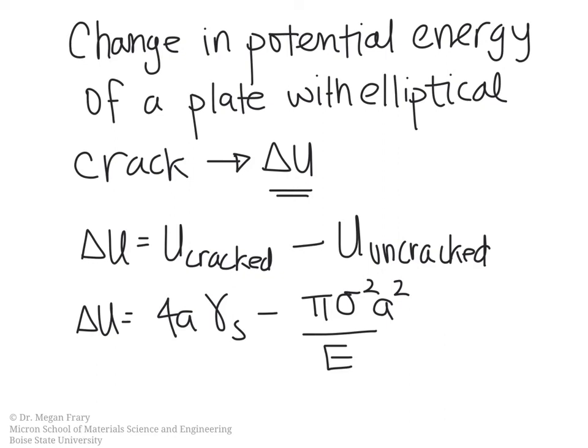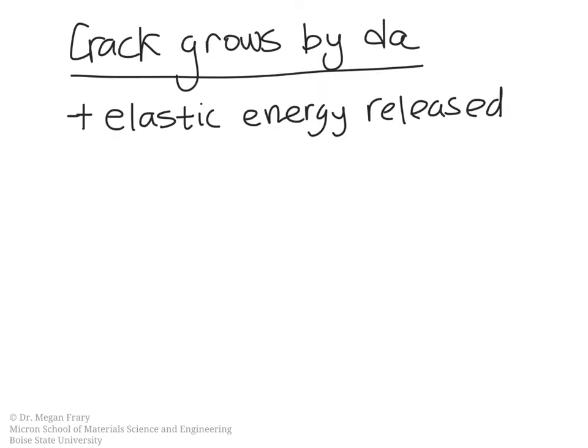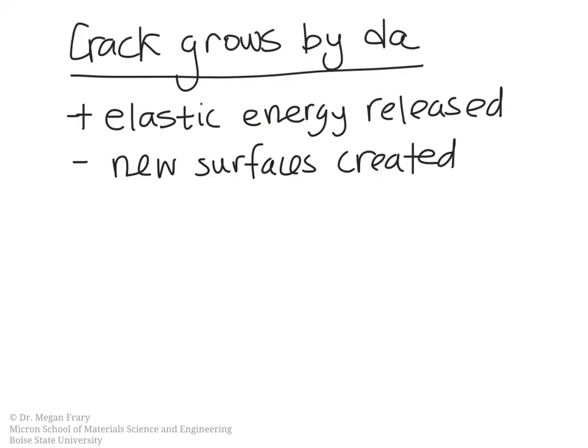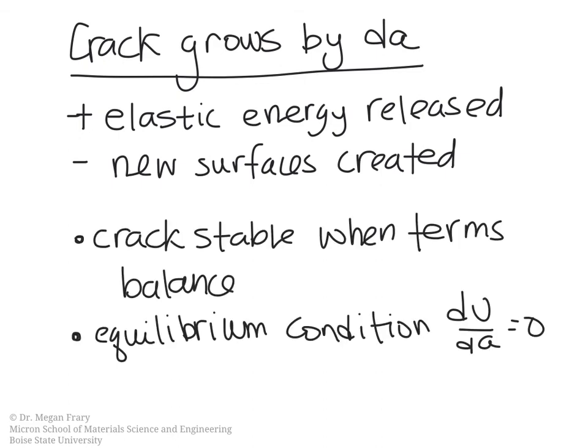When the crack grows by a small amount dA, elastic energy is released, but new surfaces are also created, increasing the energy of the system. The crack is thus stable when these two terms balance one another out. The system will be in equilibrium when dU/dA is equal to zero — when the change in potential energy with crack growth is equal to zero.